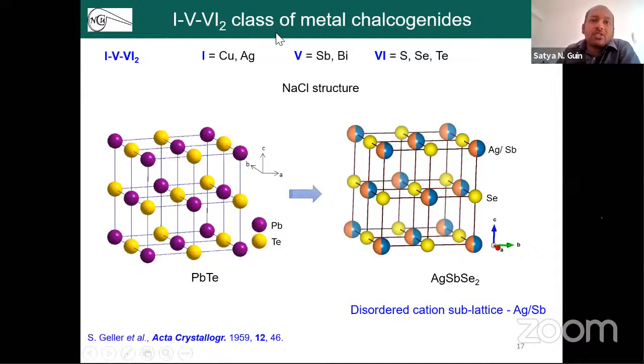This is a I-V-VI2 class of semiconductor metal chalcogenides. This material is known to crystallize in a NaCl structure, which is a standard rock salt structure. If you compare the structure with PbTe, which is a champion material considered for the field of thermoelectrics, on the Pb side you have silver and antimony disorder, and on the tellurium side, you have selenium. So it has a disordered cation sublattice in the system.